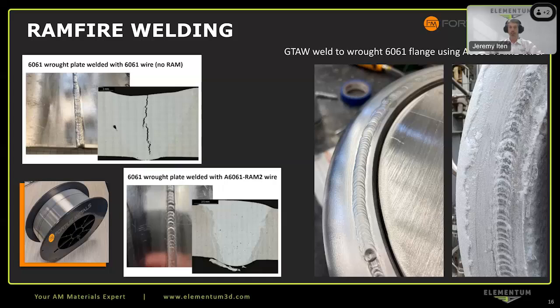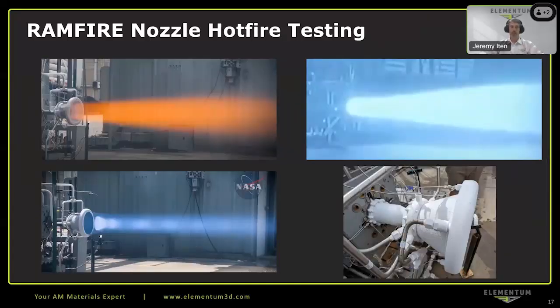You can see the image on the right. There's frost all over it. That's because of the cryogenic fuel and oxygen that was being flown through the parts during the hot firing. So here's some images from the hot firing that took place, and you can see a short video of some of the hot firing from the spin-out article I mentioned earlier. So in the upper left is the methane fuel. In the bottom left is the hydrogen fuel. And on the upper right is a thermal imaging of that methane fuel hot fire. And then you can see the nozzle and chamber in the bottom right image, all covered in frost from, again, showing the effectiveness of the cooling of the regeneratively cooled nozzle.